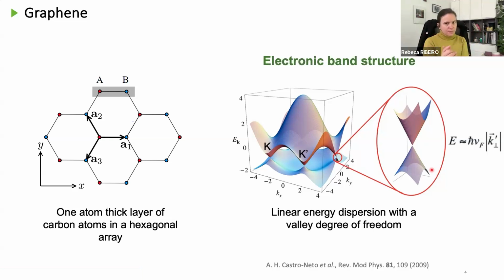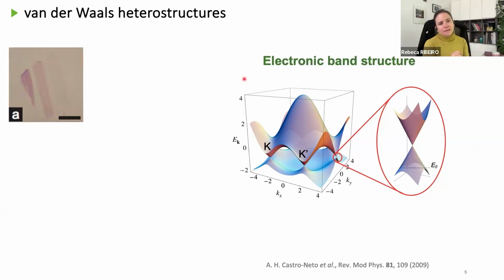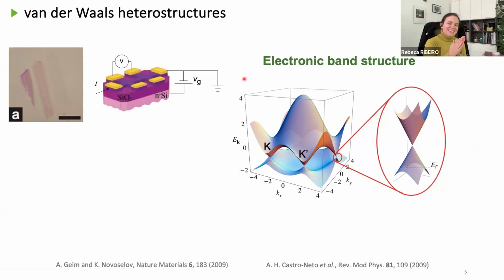We take graphene, that I already explained what it is. We know what the electronic properties are, and what we are going to do is we take the same flake, or a flake similar to the one that I had already shown you. We go to a wonderful clean room at C2N, and we make electronic devices, which means that we connect electrically this layer through electron beam lithography, metal deposition, and reactive ion etching. So once we have these electrodes contacting our device, we're going to measure electron transport, or charge transport, to be more precise. It's quite simple. For the measurements we perform, we apply a current, we measure a voltage. Seems very simple when I say it like that. It's a little bit more complicated, but we will get into it later.